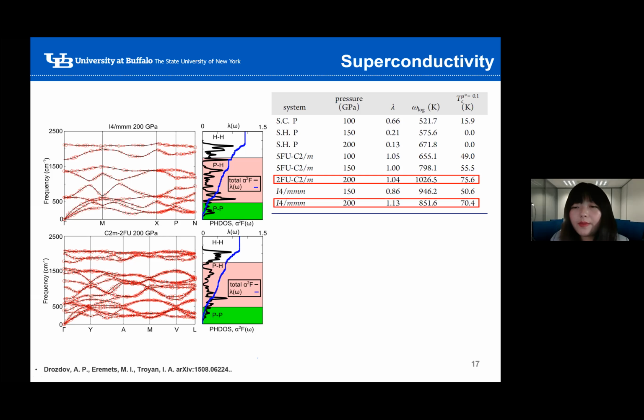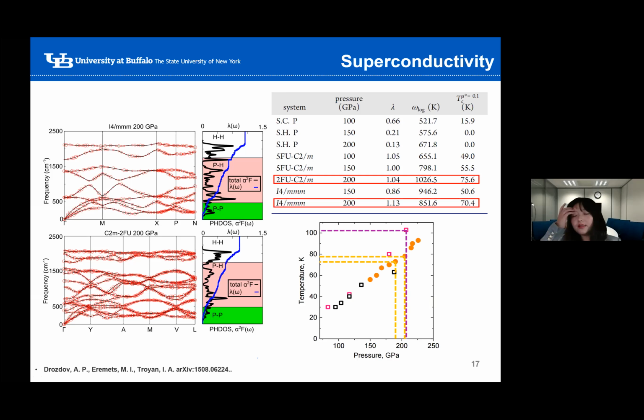So the estimated Tc values are smaller than the largest measured experimental value. However, our data matches another range in the experiments, which is colored in orange here. Also, it could be a result of the experimental measurement being taken on a mixture of metastable phases.